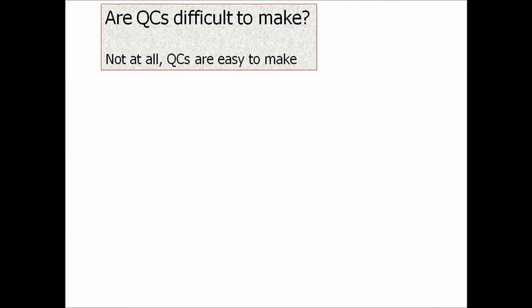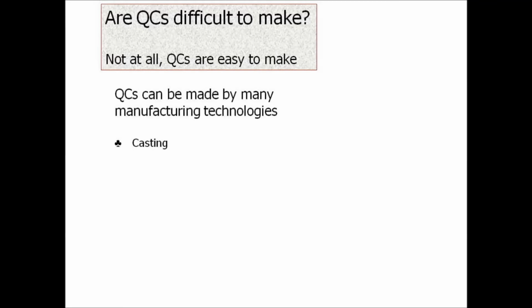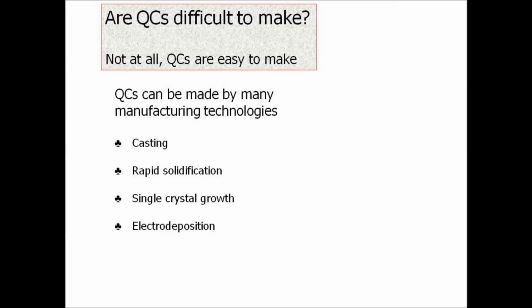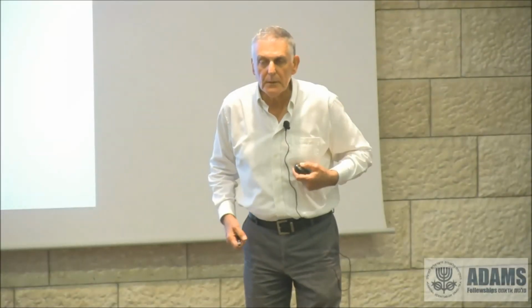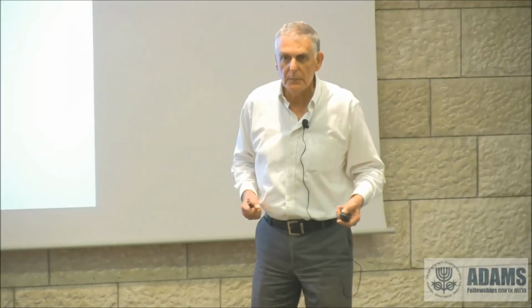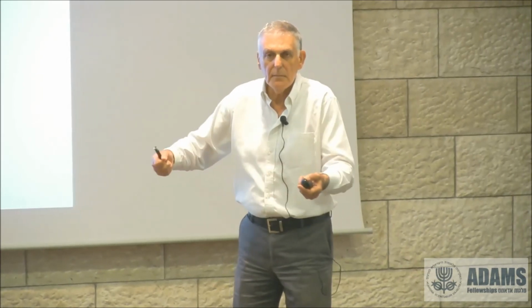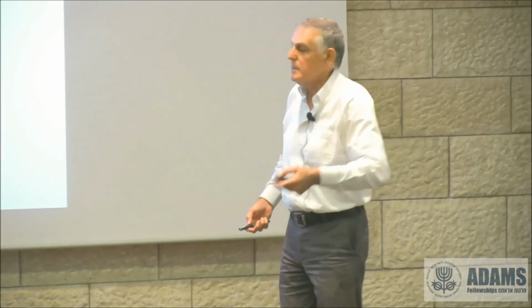Are they difficult to make? And I tinkered one of them. Not at all. They can be made by many manufacturing technologies. You can cast them, you can rapidly solidify them, you can grow single crystals, you can produce them by electrodeposition, by CVD, by PVD. Any technology, you make any alloy or any intermetallic compound, you can make quasi-periodic material. It's easy to make. People repeated my experiments a few days after the publication. They did the same. They had it. A few days. Easy.